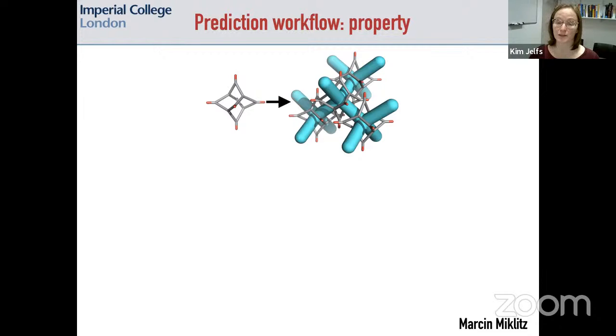So the 2 cages line up window to window next to each other, and therefore you get a diamondoid pore network. What I'm about to say next would apply whether or not you have a diamondoid pore network, but the key point that we identified is that if you really analyze the individual molecule and its structure, its void sizes, its cavity, etc., then you are actually analyzing all the key features that you have in the solid state in this case.